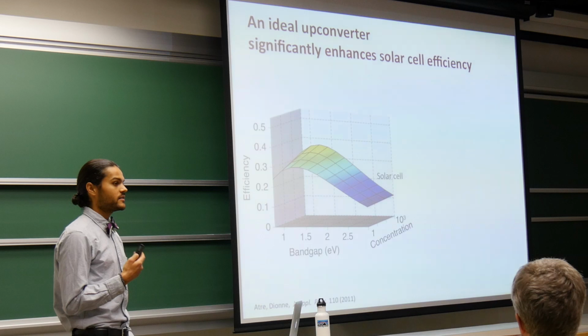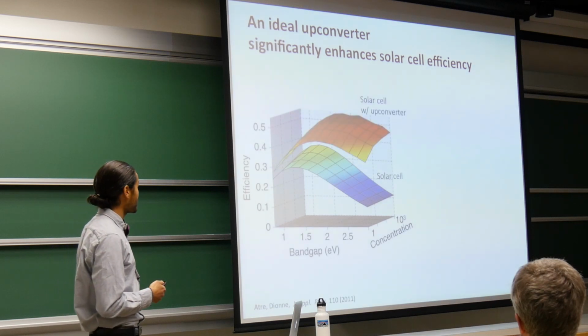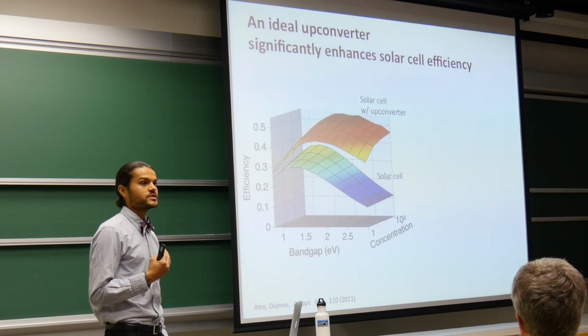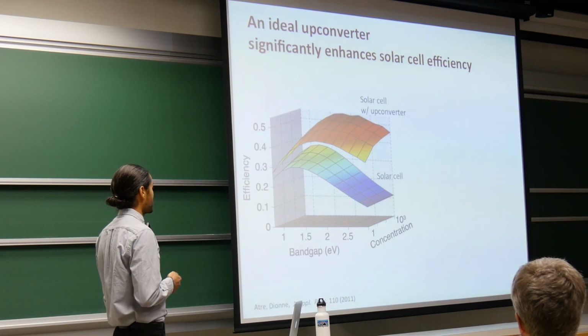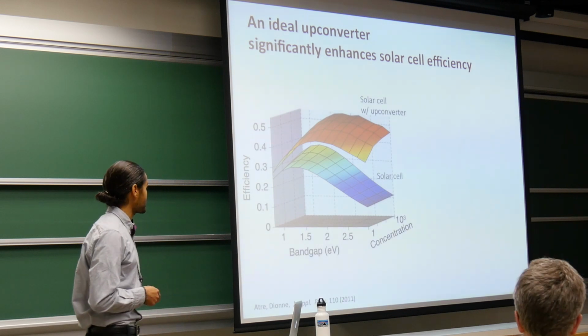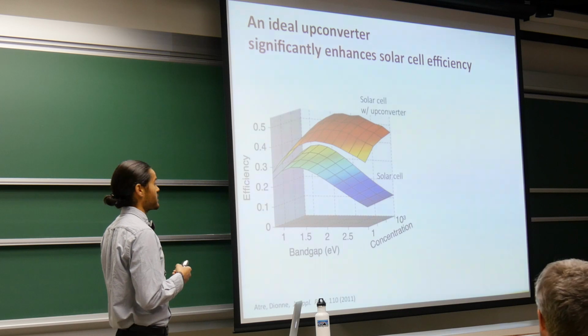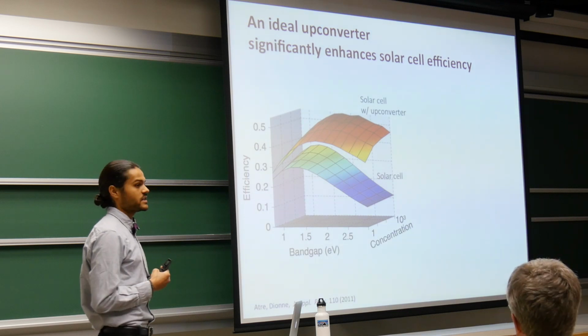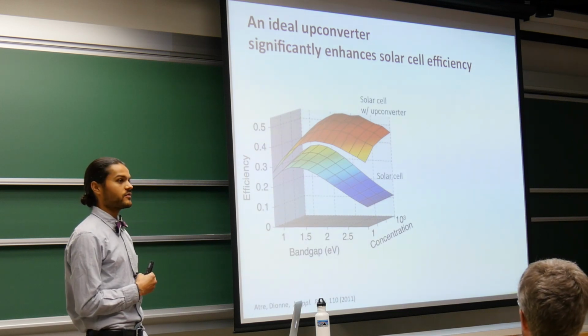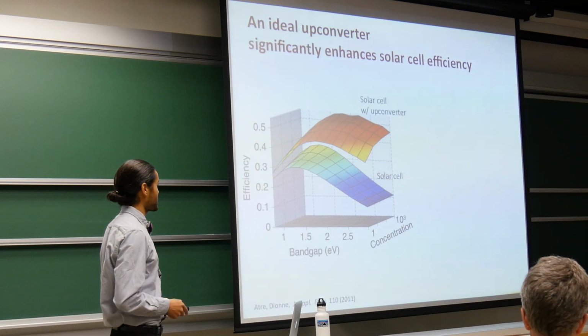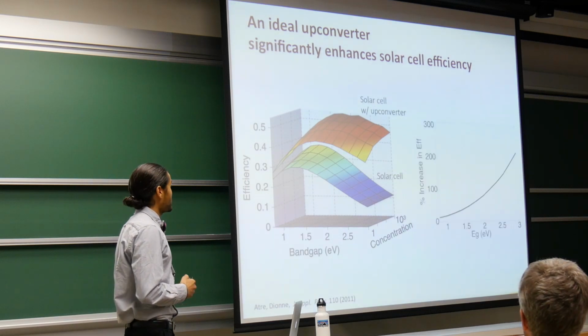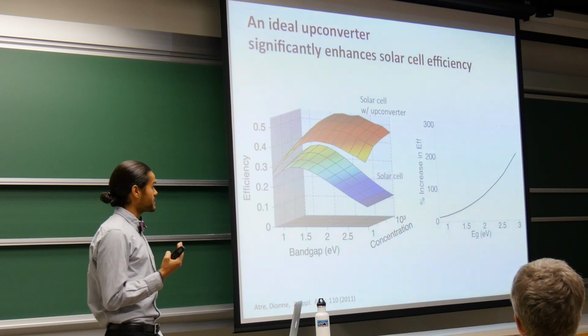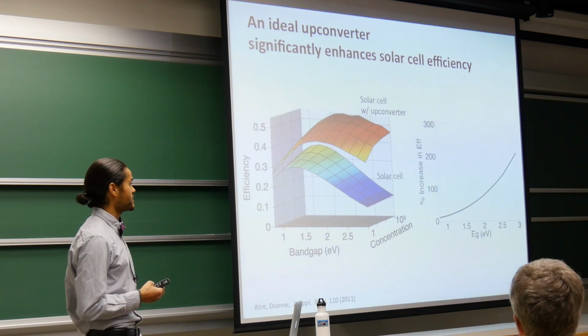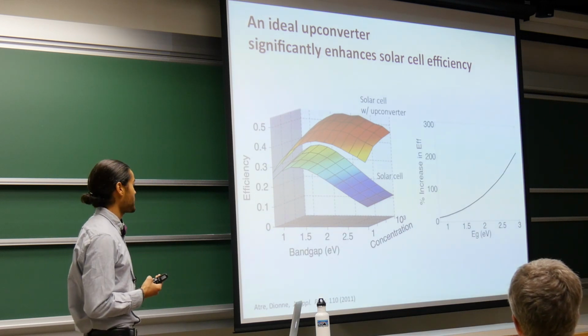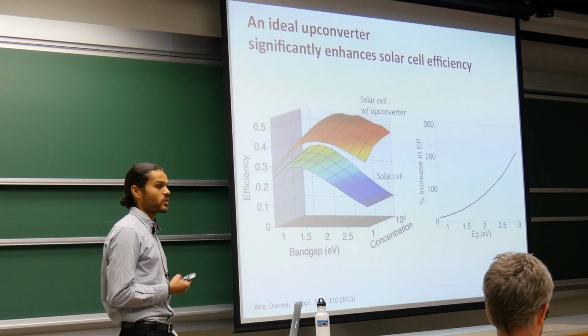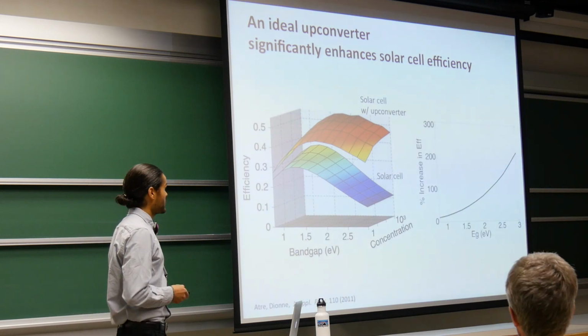Now, if we add to this ideal solar cell an ideal upconverter, we find that the efficiency is boosted across the board, for all the range of parameters that I've shown here. In this case, for non-concentrated sunlight, the efficiency is increased from about 30% for a single solar cell to about 44% for the combined device. Interestingly, and actually as we expect, the relative increase in efficiency is largest for large band gaps because more photons are wasted the larger the band gap you have.